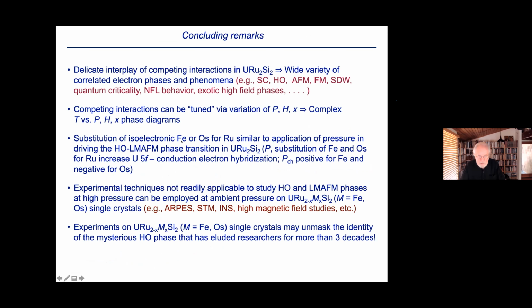And substitution of iron or osmium would probably seem to be not very fruitful at the outset, because it's an isoelectronic substitution, but it's similar to applying pressure. And also it gives you some insight into the mechanism that's driving the transition for the reasons that I've tried to discuss. And so the other thing is that by being able to do this isoelectronic substitution, and drive this transition at atmospheric pressure and do this in single crystals, then you do have the opportunity to apply some of the especially spectroscopic types of experiments or techniques to studying hidden order in this material.